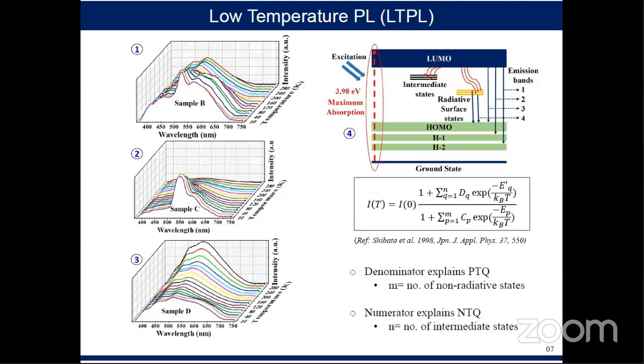To explain that, we have to take help of the band diagram in figure 4. As I said, sample D contains the smallest nanocrystals, which have the highest surface to volume ratio. So there are lots of functional groups attached to the surfaces, which contribute a lot of intermediate states. They trap the electrons while transiting from LUMO to HOMO band. But at lower temperatures, the detrapping is not allowed. As the temperature is raised, they get enough energy, get activated, and transit radiatively. So they increase the photoluminescence intensity at higher temperature.